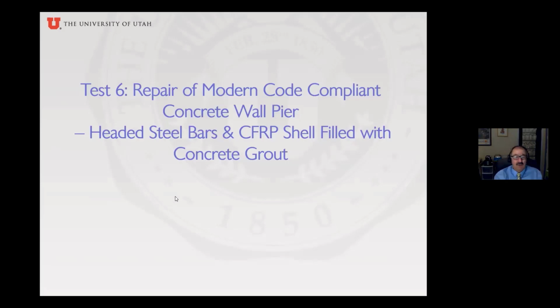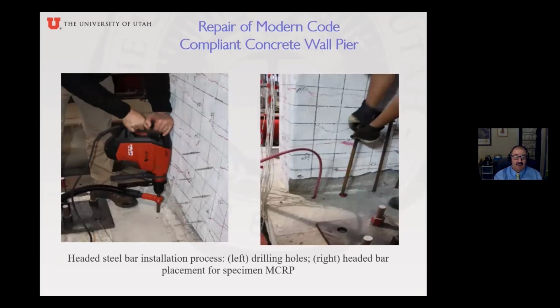So I'm going to show you, and then you will realize this is a donut, but it's an elliptical donut and not a circular donut. Because remember, our wall is 4 feet by 1 foot in cross section. So here drilling is easy because you drill away from the wall and you put in the headed steel bars. These are grade 60, very easy to install. Drill the hole, put a little resin first, then push it in until you see the resin come out. Then you know that this was done properly.